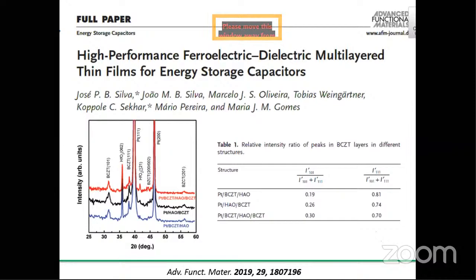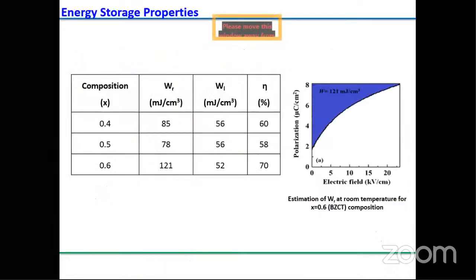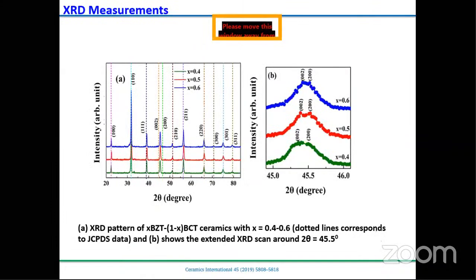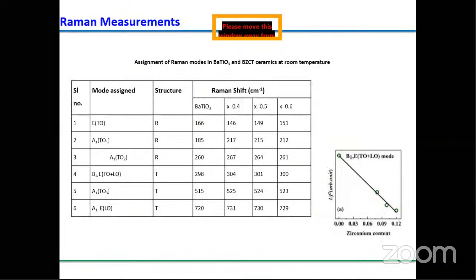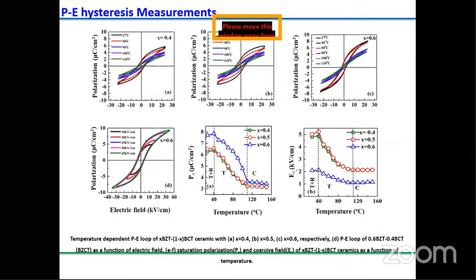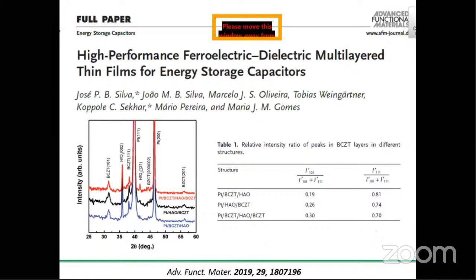So here, what is our idea? Our ferroelectric properties depend upon the orientations. When we observe bulk materials, different kinds of reflections are there: 100, 110, 111, 211, like that. If I can grow the entire film in only one reflection, that is what we call epitaxial films. They behave like a single crystal. In thin films, the terminology is epitaxial film. That means they are oriented in a single orientation. If you can make your films oriented in a single direction, that will help to improve the ferroelectric properties. That is the strategy I am going to apply here.